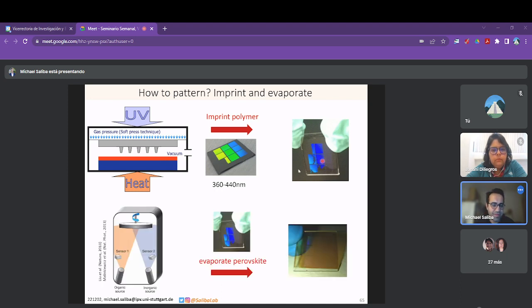And then on the polymer, unfortunately, we cannot deposit the perovskite directly because it's dissolved in DMSO, which in turn would dissolve the polymer as well. So instead, we decided to evaporate the perovskite. You see that here. And here, when we perfected our method of imprinting the stamp, the perovskite, you can see it here, is directly on top of the stamp.